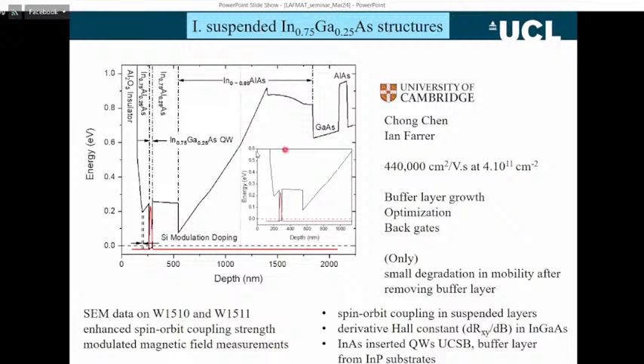The inset here is a blow-up of this device. So this is the confining potential now. This is energy on the y-axis as a function of distance from the surface. And the charge itself is just confined to the two-dimensional region here. What we found in this work is that these are very, very complicated structures. They're difficult to grow. We've got the compositional grading in the structure.